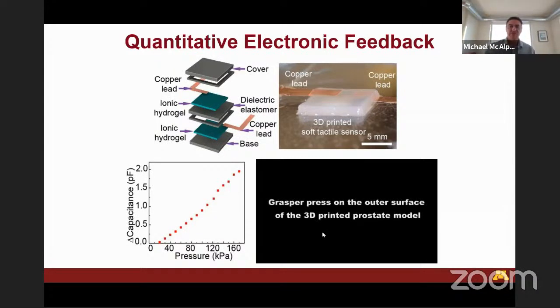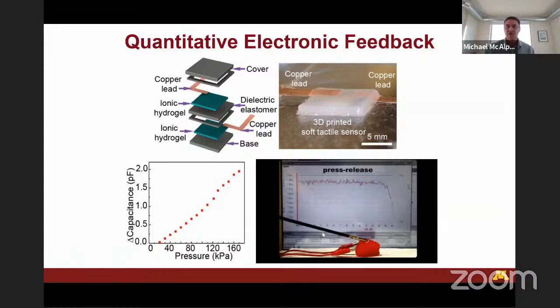And so we can do a calibration curve with the applied pressure and measure the capacitance of the structure, so that we can print these things and then incorporate them onto our soft organ model, so that you have this electrical feedback, right? So as you're doing this faux operation on the organ model, it'll actually give you quantitative feedback based on these 3D printed ionic hydrogel sensors that are incorporated on the model and also inside the model as well. So now we're building complexity here.